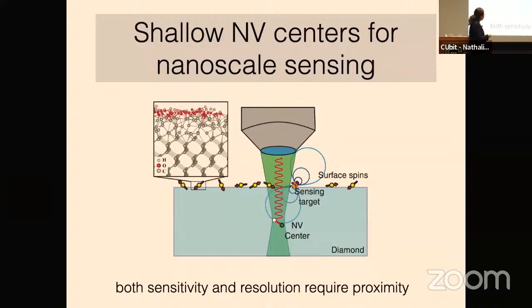So the problem is that while these NV centers deep in the bulk of diamond can be really exquisite, when you get close to the sensing target, you also have to get close to a surface. And in general, I would say that mankind is quite bad at surfaces. And in particular, we are really, really bad at diamond surfaces because diamond is the hardest material in the world. So even doing things like polishing, and just preparing a nice surface are very non-trivial.